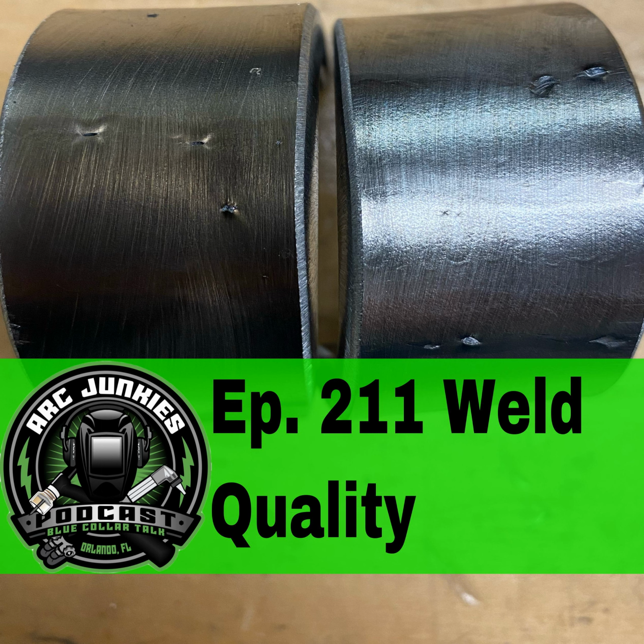I talked about this in, I believe, Just the Tip Tuesday, episode number 1, the biggest myth in gas metal arc welding. So go check that out if you're not too familiar with how all that works, but your wire feed speed is going to increase your amperage. Likewise, a travel speed that is too fast is going to cause incomplete fusion, because once again, we didn't give our electrode enough time to do its job, where it has to melt the base metal and melt the filler metal.